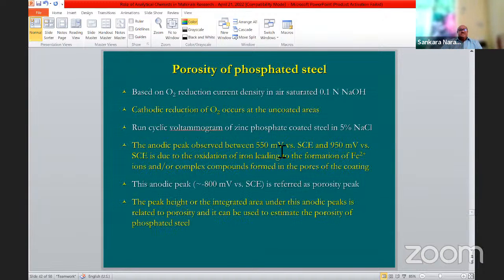So the method is based on the oxygen reduction current density. You can take an electrolyte like 0.1 normal sodium hydroxide solution, and there will be cathodic reduction. Dissolved oxygen will be there in the solution. So when you run a cyclic voltammogram, oxygen will reduce, and that will generate a current density. So the cathodic reduction of oxygen occurs at uncoated areas.